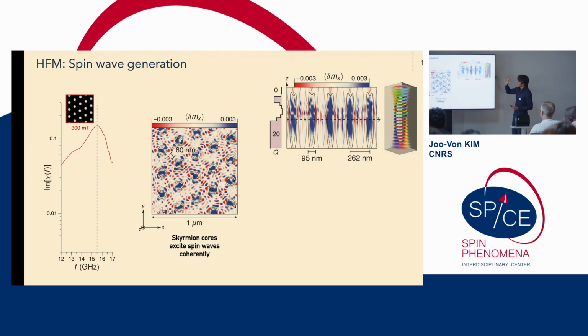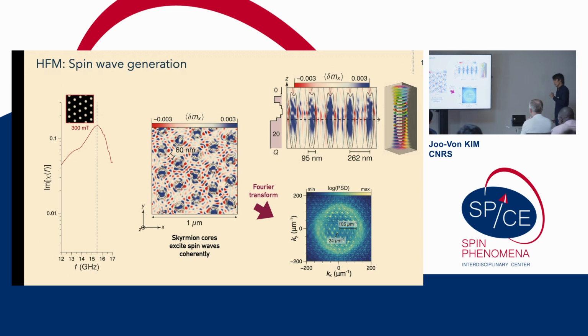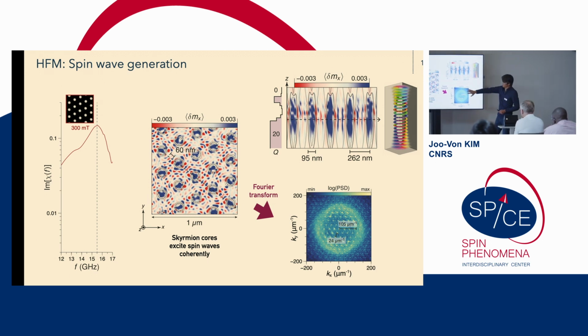And what is kind of interesting is that I've reproduced this cutout of this three-dimensional skyrmionic texture, where I showed you before that it is mostly topological below, not so topological above. But it doesn't seem like it plays a large role in this spin wave emission picture, where we can see that it works just as well below as it does above. And if you take a Fourier transform now of just this image here, you can get an idea of what the wave vector is.